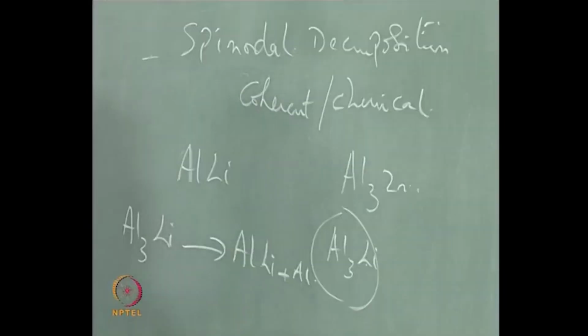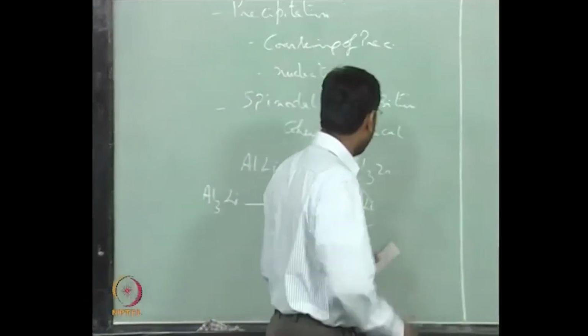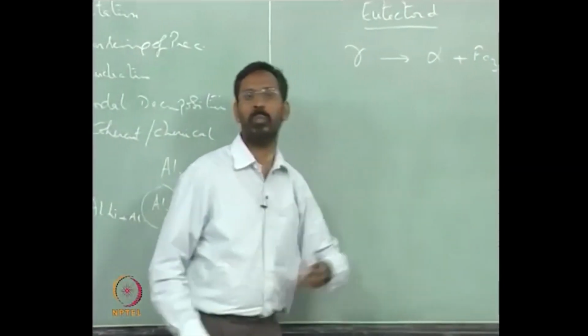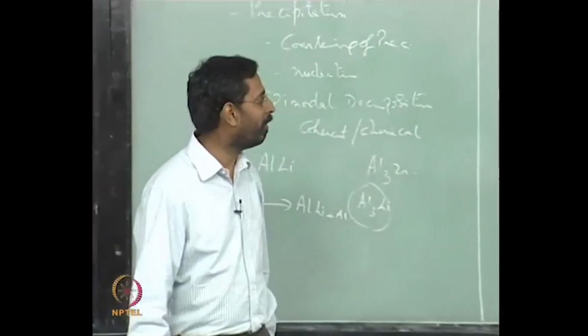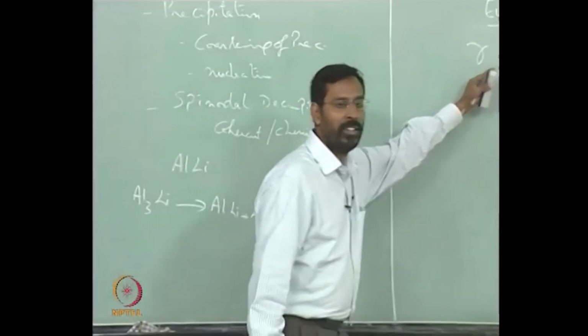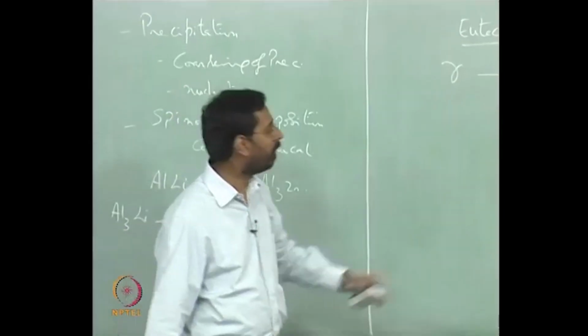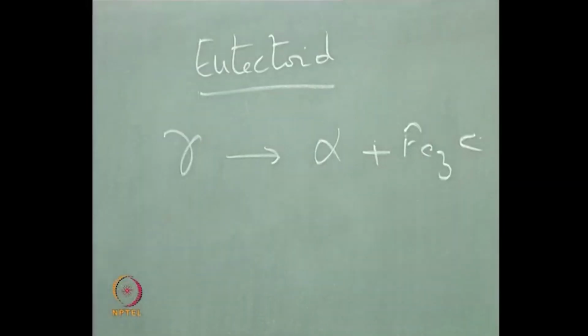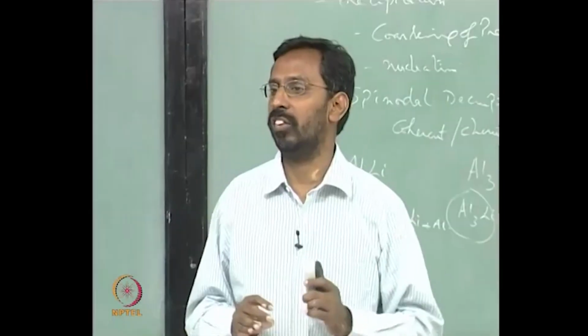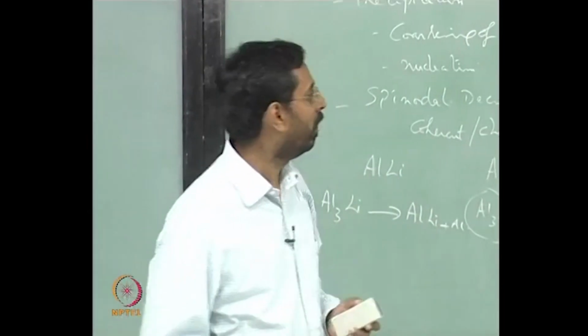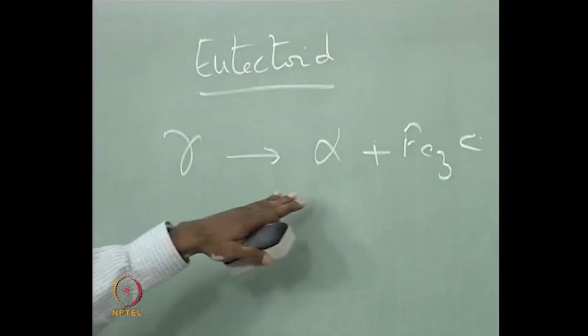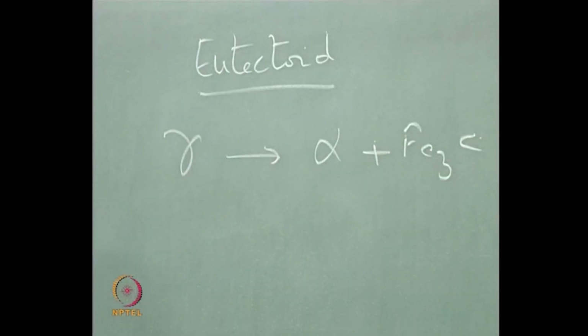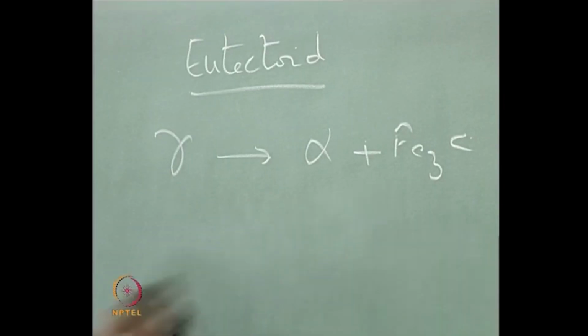One example is aluminum copper itself. Now if you come out of a normal precipitation and look at this case, the difference between this and this that we talked about so far is that in this the two phases that are coming out have different compositions, and in a number of cases they have different crystal structures. In fact, in most of the cases they are different crystal structures. There can be some cases where the structure of one of the phases could be the same as the matrix, but in a number of cases you will see the structure is also different.